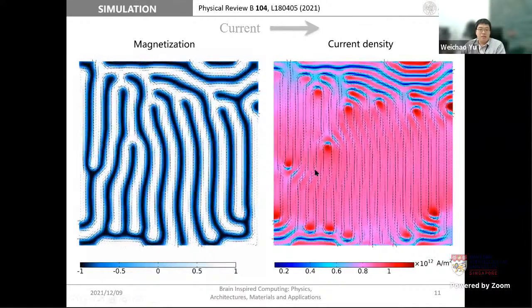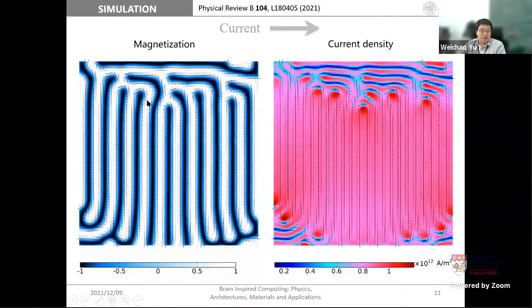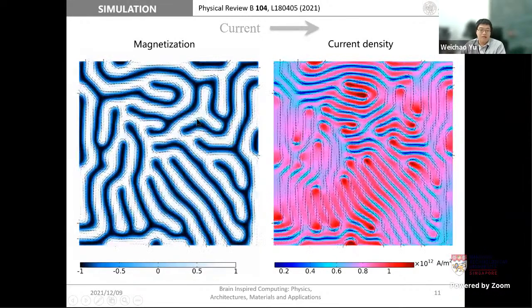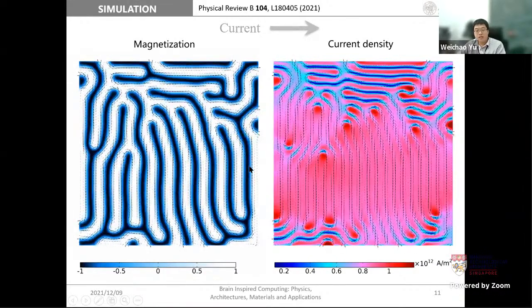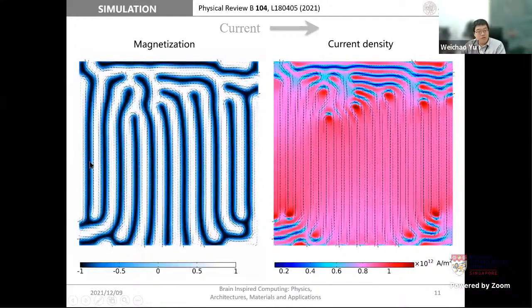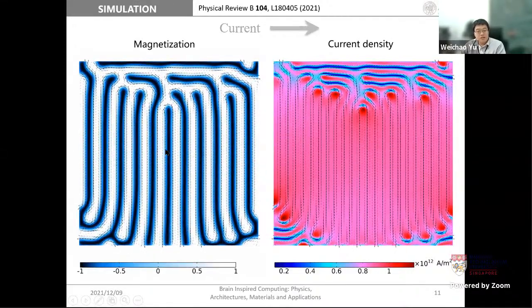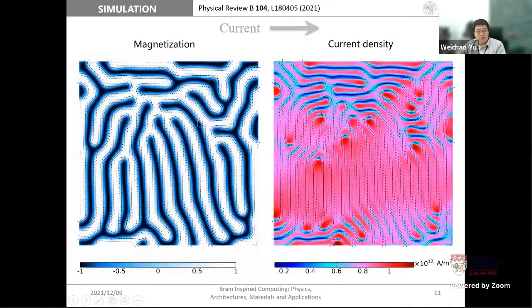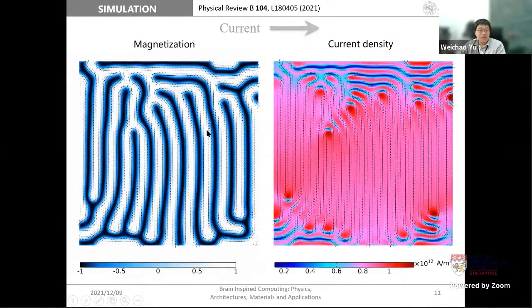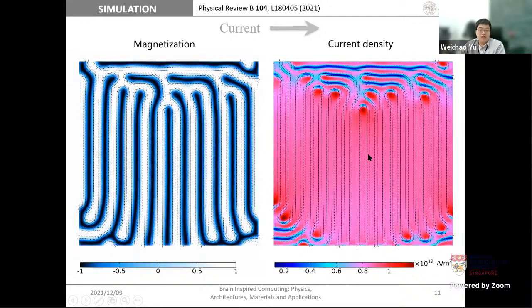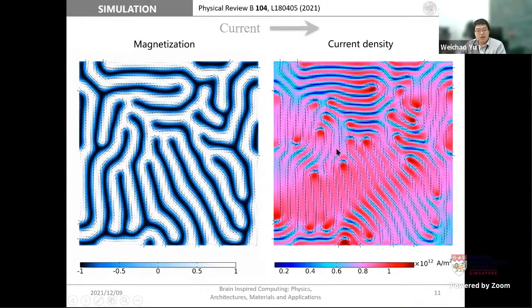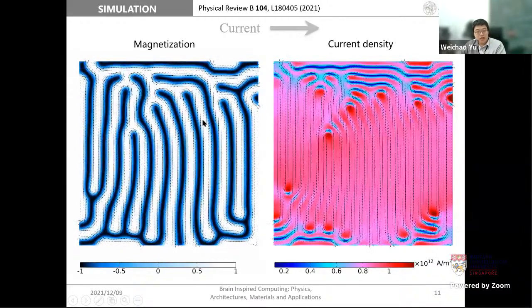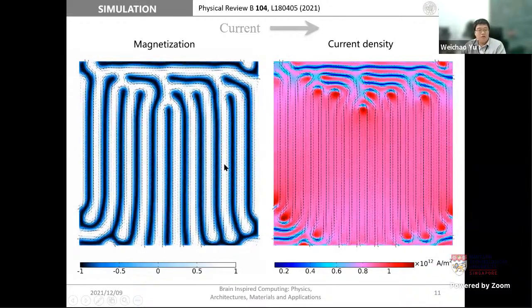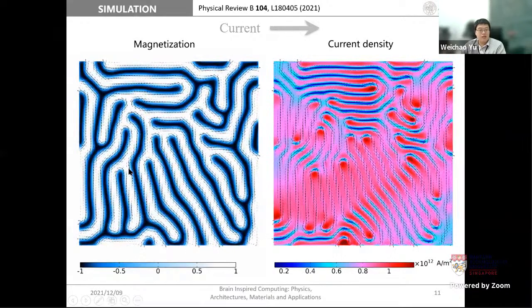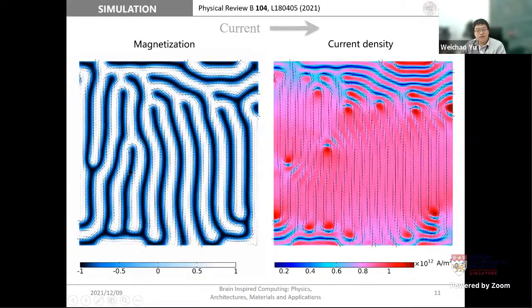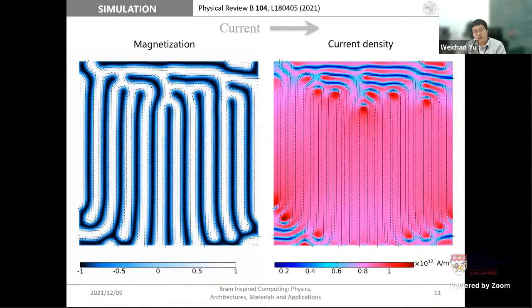This is a micromagnetic simulation. For this square film, we apply voltage difference on the left and the right edge so that the current flows from left to right. The left figure plots the magnetization configuration, and the right one plots the current density. In the presence of spin transfer torque, we can see that the stripe domains will finally be aligned perpendicularly to the current, and it finally becomes stable after sufficiently long time.